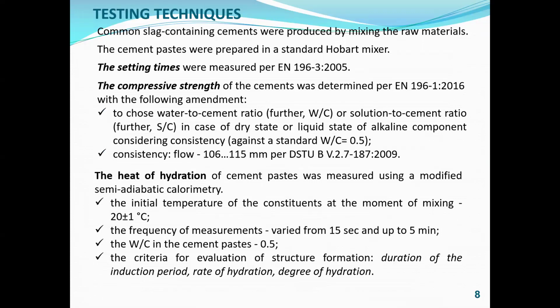Testing techniques. The compressive strength of the cements was determined by EN 196-1 with the following amendment. A water to cement ratio was chosen in such a way that its consistency, evaluated by flow, would be 115 millimeters against a standard water cement ratio of 0.5. The heat of hydration of cement paste was measured using a modified semi-adiabatic calorimetry.